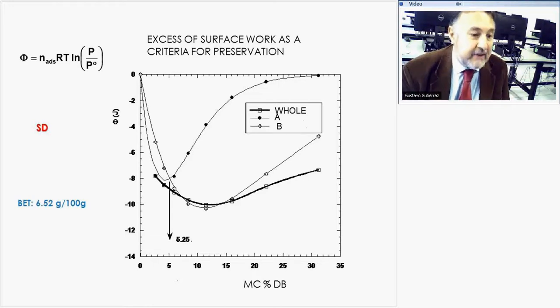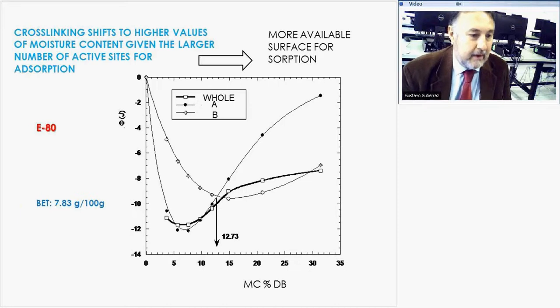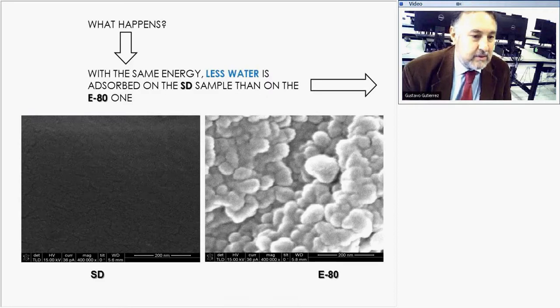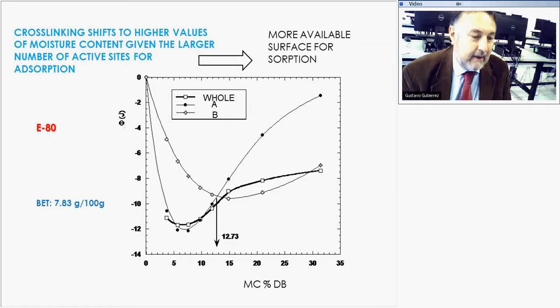But this shifting occurs at values of moisture content, of course, higher. You see here that it goes up to 12.73 and the monolayer rises to 7.83. What do we mean? It means that more active sites were in the material as compared to the material with the structure. So here is the ethanol at minus 80, and this is the spray dry one. These values increase when we fabricate at minus 80 degrees, with more active sites of sorption.